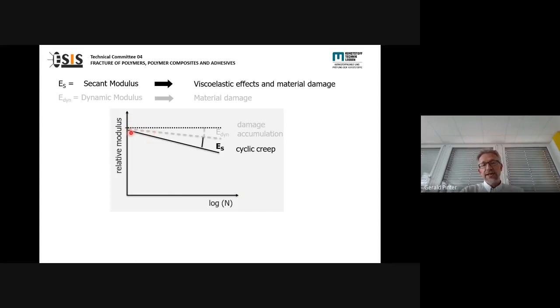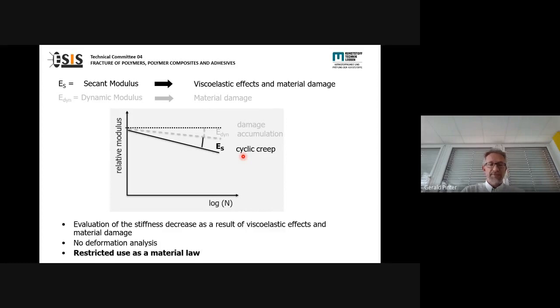And typically the secant modulus is always lower than the dynamic modulus because it covers creep and damage. The dynamic modulus, based on the definition of the two moduli and the calculation of the moduli, only covers the change in the slope of the hysteresis. It does not cover the creep aspect of the polymers. So by comparing these two moduli, you can get an idea about the relation between cyclic creep and damage accumulation.